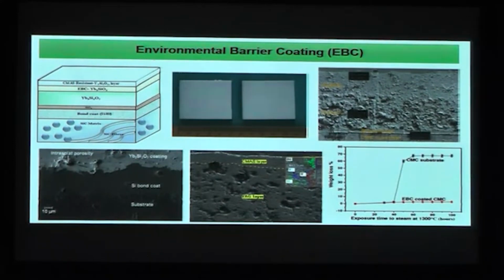Further, a different type of coating has evolved. Here you can see these are all ytterbium silicate based coatings. So it's once again a multi-layer coating. Here we have also given a YAG based CMAS resistance coating. This is mainly to protect the engine components from the CMAS attack, which is mainly caused by volcanic ash. And here you can see this coating is very much more durable compared to the bare CMC substrates.